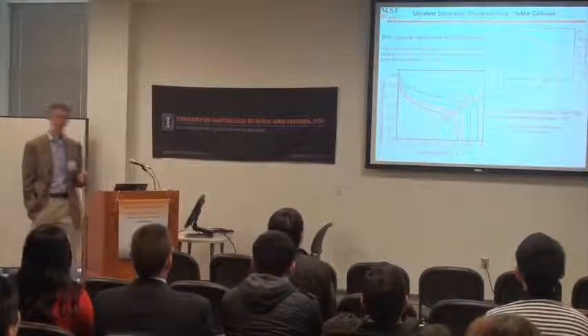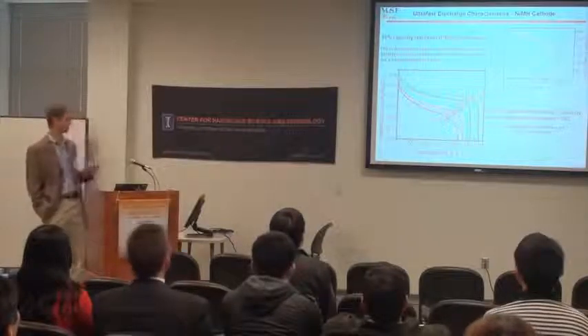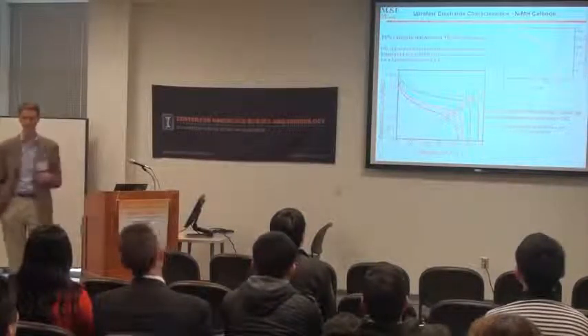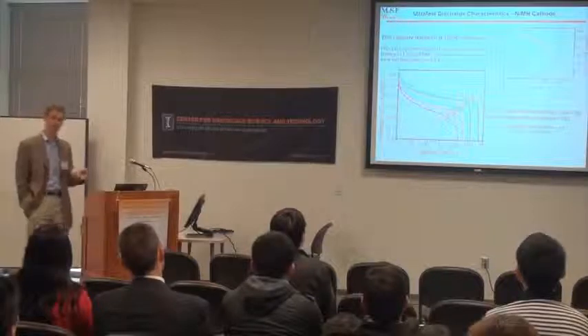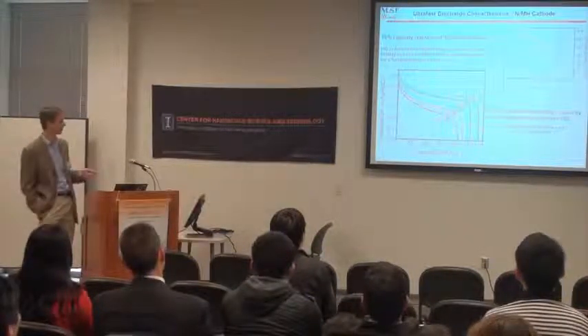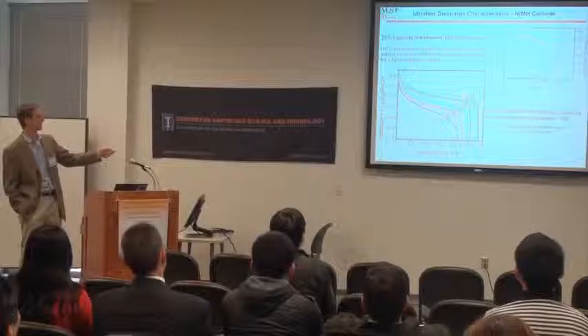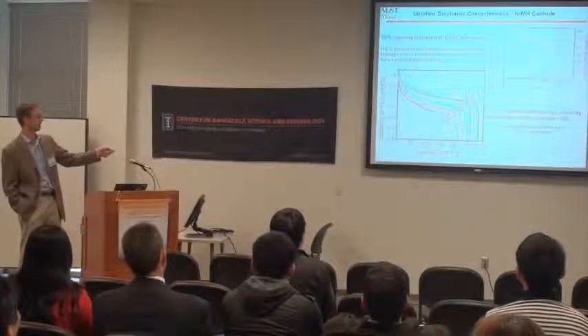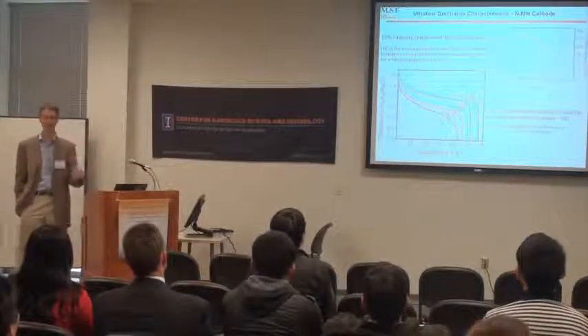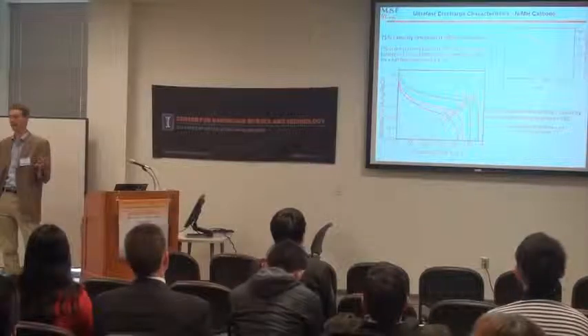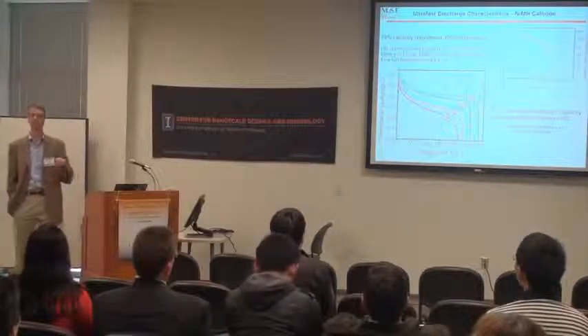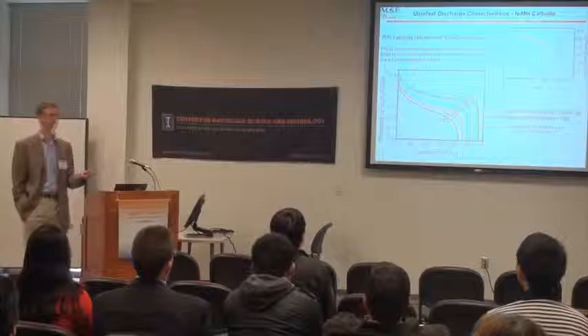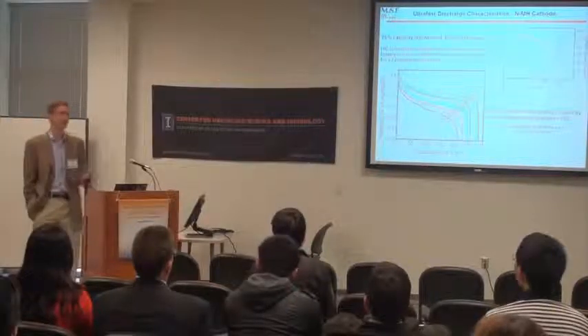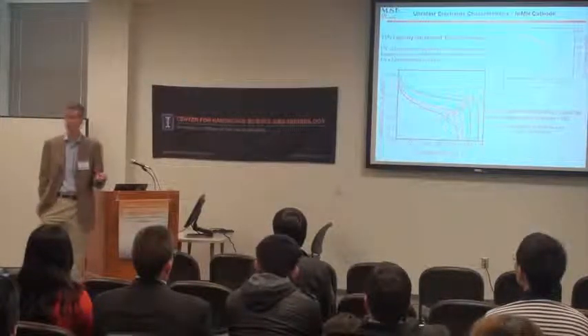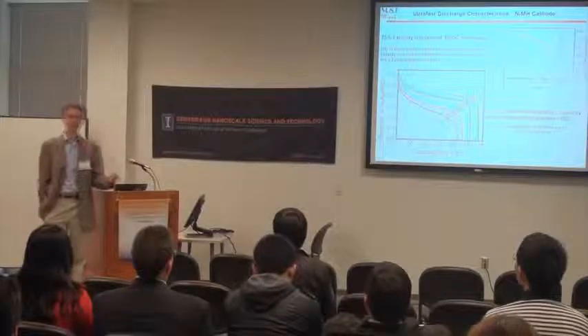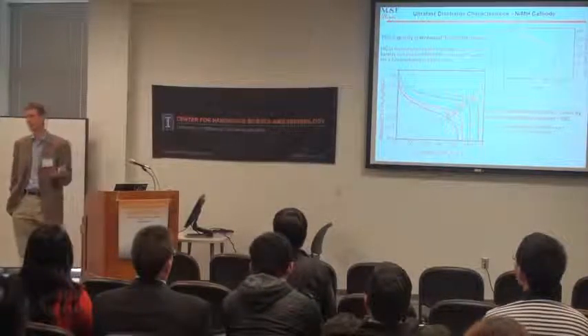So what becomes interesting is if you take, and this was our first battery, a nickel metal hydride system, the one still used in hybrid vehicles, not really in portable electronics anymore. Normally if you would take this battery and discharge it, a 1C discharge means 1 hour. If you take an hour to discharge a battery, you'll get most of the energy out and you can charge it up. I'm sure you're familiar with that. Your laptops or cell phones typically take about an hour to charge.